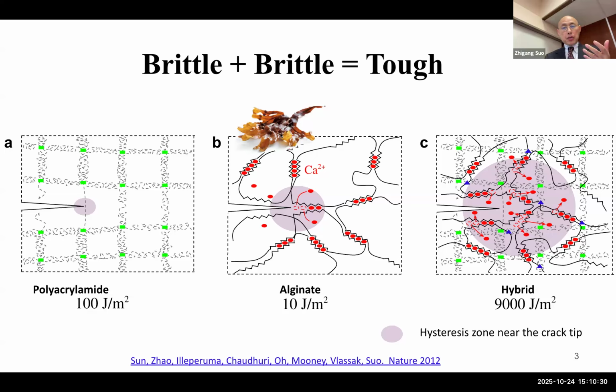Alginate is a tofu-like material coming from seaweed. It's a biomaterial. So this alginate has long chains. Between the chains, the crosslink is not a covalent bond. It's a calcium ionic crosslink. So the material is also brittle, because a crack will unzip calcium crosslinks and propagate forward. In propagating forward, the other calcium crosslinks remain intact and don't contribute to the energy dissipation.